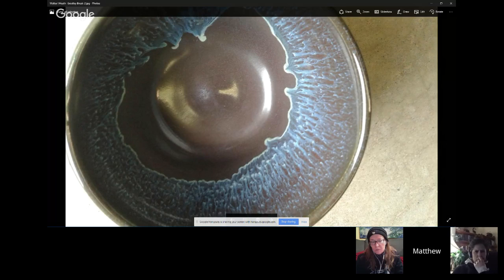And I should say, if you overload the system, you can insert as many boron molecules as you can, but there's still a finite number. And so the remaining boron molecules will do something, and in this case, they'll phase separate, where they will make a relatively stable glass all on their own that's literally living hand in hand with the original glass. And so it's cool for an effect. And again, it comes down to this conversation about durability and the quality of the glaze. But a lot of the conversations we can have now is, well, you're aware of durability issues. So we can talk about doing cool decorative things that may or may not be stable in the greater sense of the word.